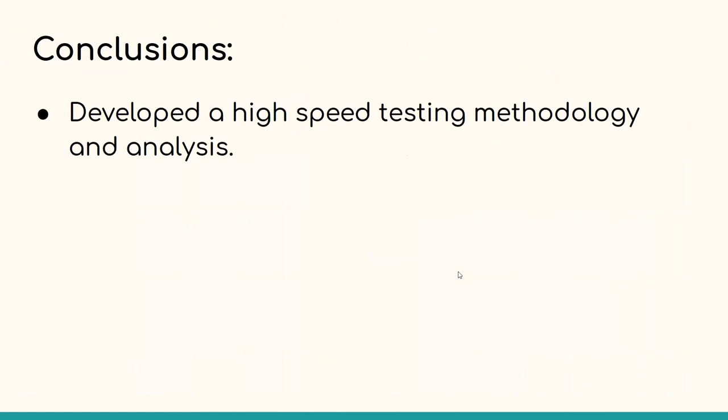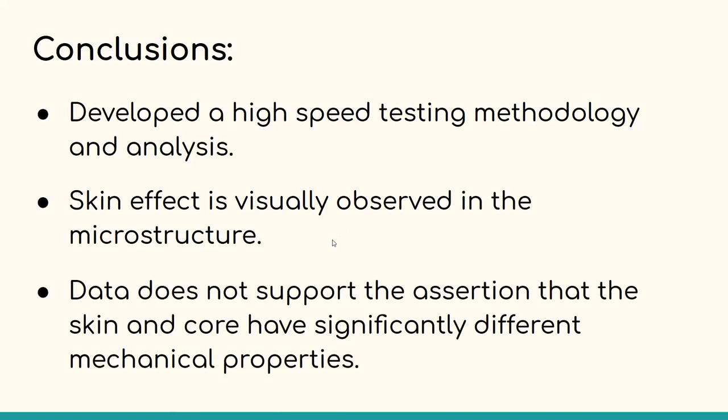We concluded that a high-speed testing methodology and analysis was developed to accurately map the sample's cross-section. The skin effect was observed visually in the microstructure of the samples through optical and SEM metallography. However, no significant difference in the mechanical properties was determined between the skin and core.